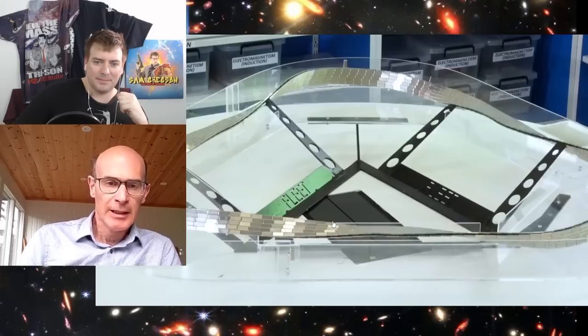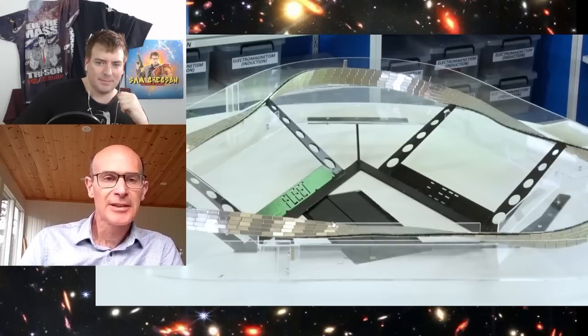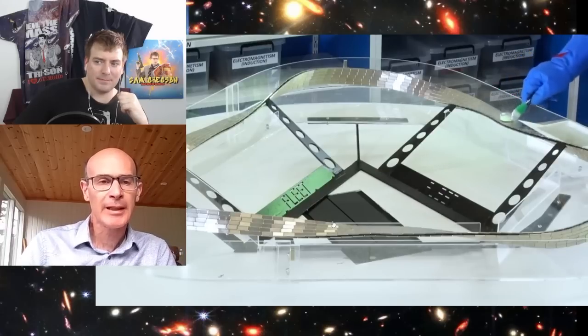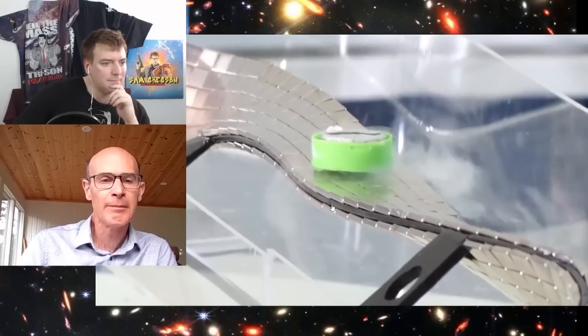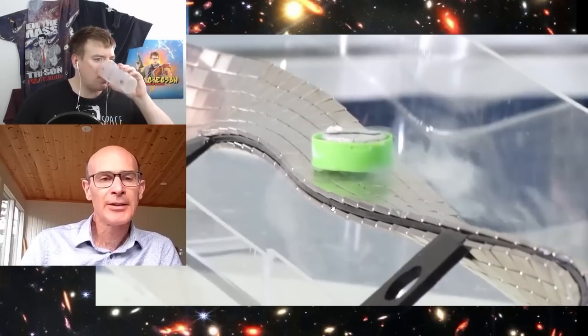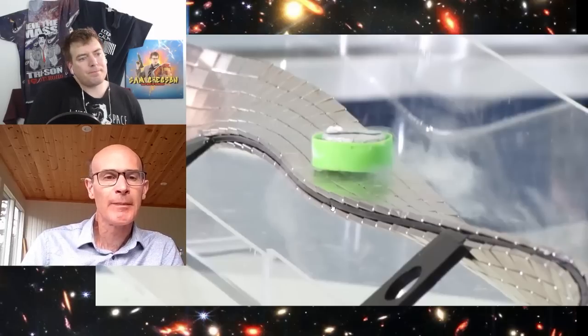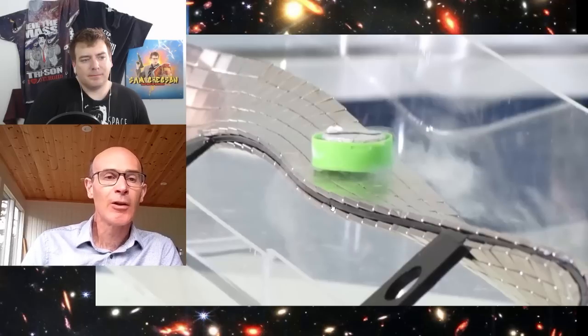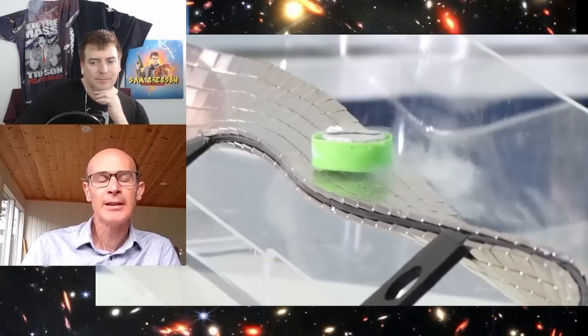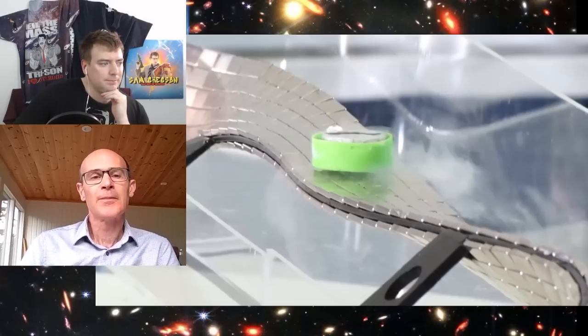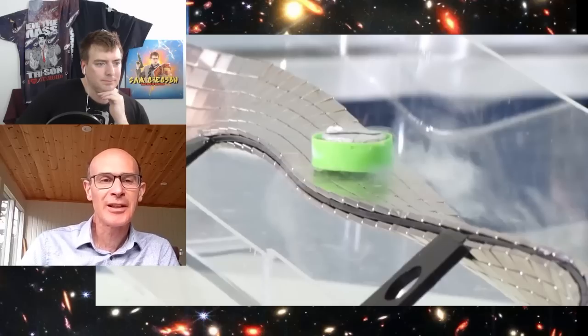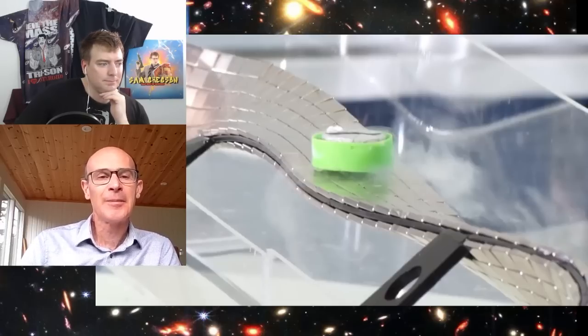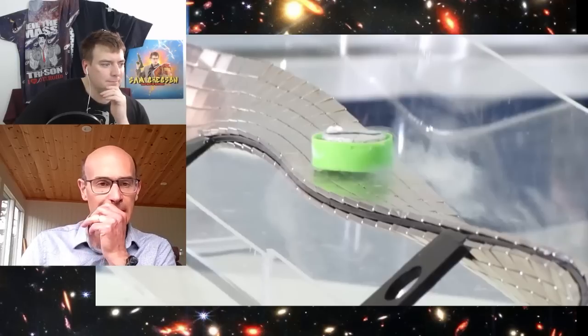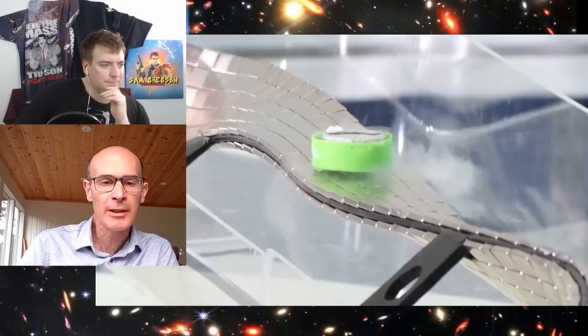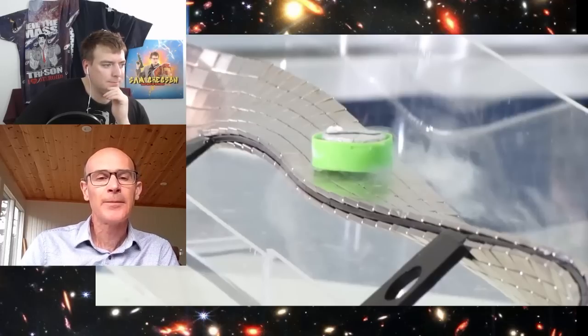they've cooled the material into the superconducting state while it's being exposed to the magnetic flux of the magnets on that track, and as I mentioned, that flux penetrates the superconductor slightly, so it gets locked into the magnetic field of the track. So you should be able to do that if you were to take this new material, heat it above the superconducting transition, cool it down on that track, and then you should get it to race around the track, but without the need for cooling it. They've got some sort of onboard cooling on the piece of superconductor in green there.